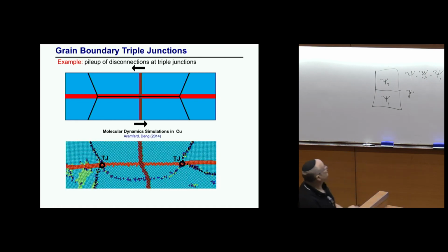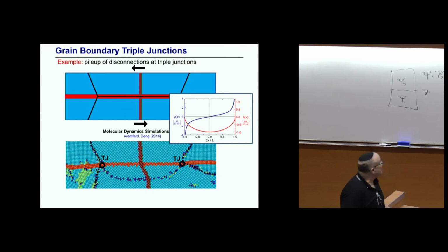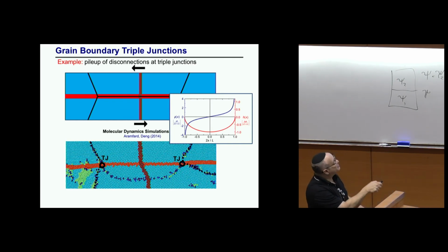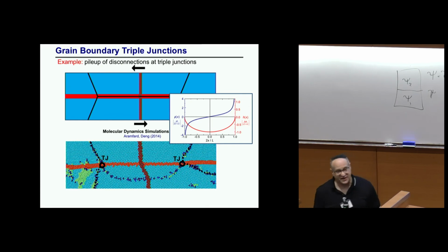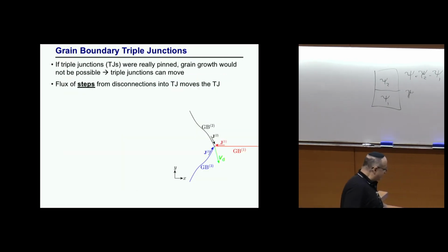And this is actually the simulation result. And you can see this line here. So these are the grain boundaries afterwards. That's the final profile. This is where this grain boundary was initially. You can see the lattice is sheared like that. And that's the final profile. And that's the prediction of what it looks like, if I plug in which Burgers vectors and step heights are allowed for this grain boundary. This has no adjustable parameters.